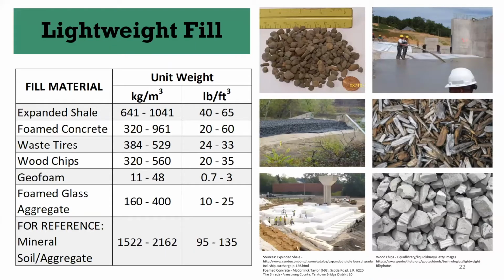All right, and here's just another slide showing you a comparison of some of these materials. In the upper left, this is an expanded shale type of product. In the upper right, I didn't mention this previously, but there is a material called foamed concrete or cellular concrete that is used as well as a lightweight material. Foamed concrete is made by mixing a foaming agent with cement and water, and then spraying it out like you see happening in this picture. And they can really dial in their unit weight. So they could be as light as, say, 20 pounds per cubic foot, or as heavy as, say, 60 pounds per cubic foot.